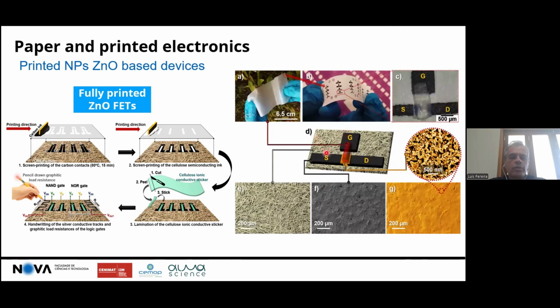The paper is the substrate. The semiconductor layer is in between, and you have the dielectric, or the electrolyte in this case, connecting the channel region to the gate. And you see here a real photo of the device, and you see also the SEM micrographs of the surface after printing the zinc oxide layer, before putting the dielectric. So this is the paper, this is after printing the electrodes, and this is the paper coated with the zinc oxide layer.